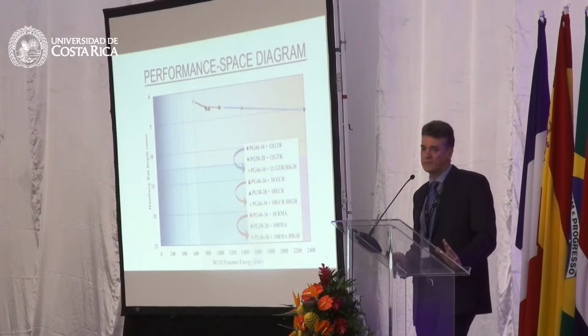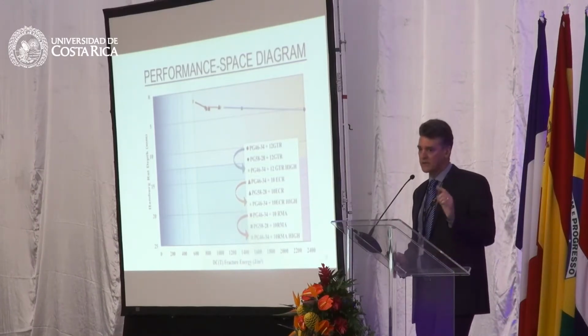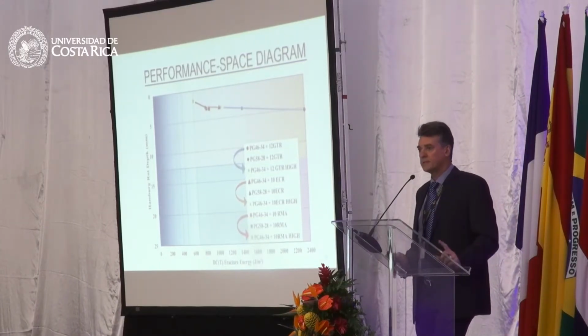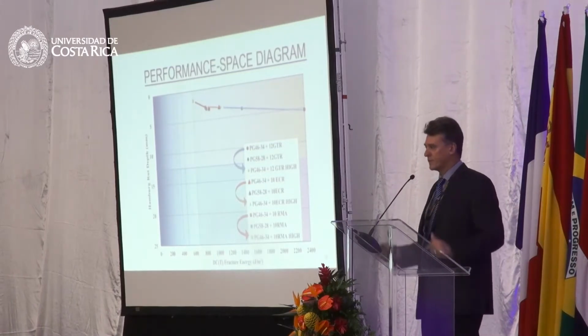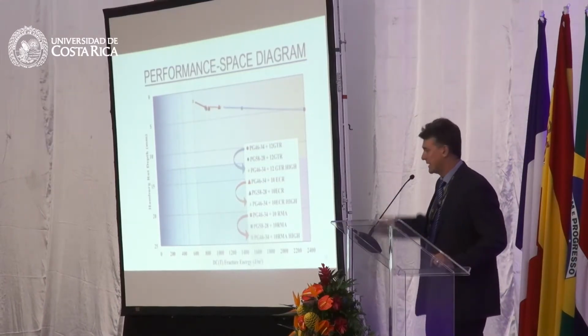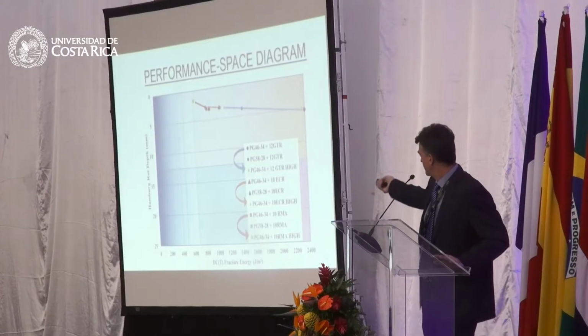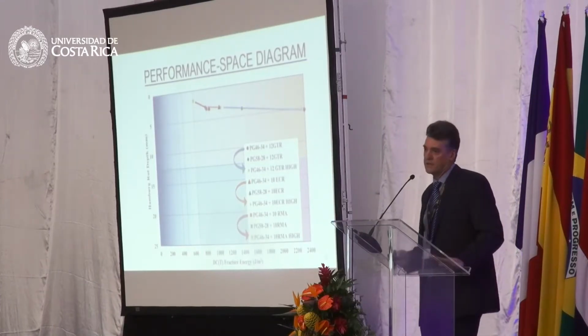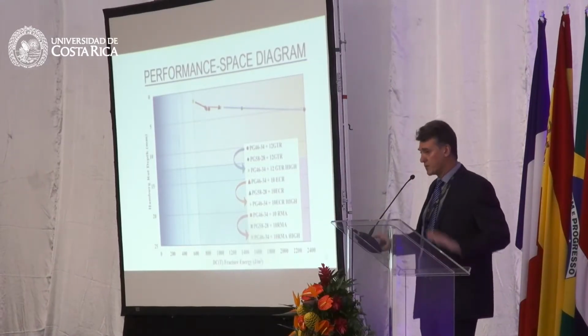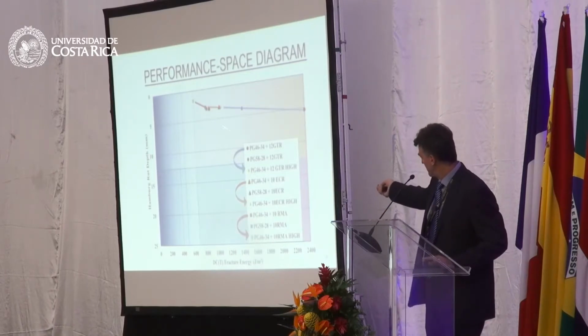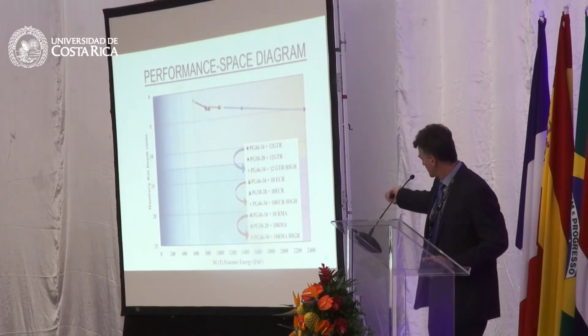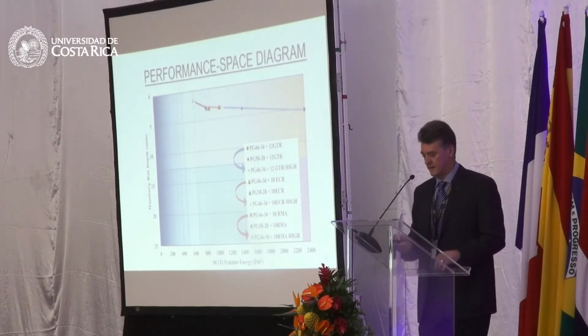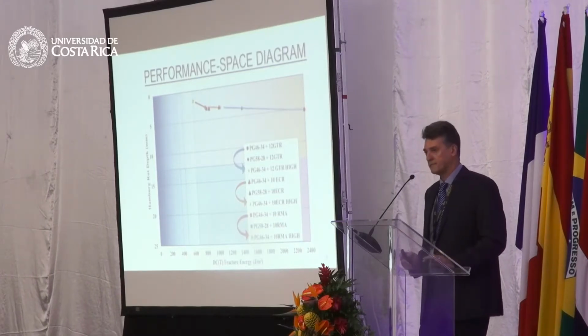It may be that we've been designing these mixtures a little too stiff. They seem to be very tolerant to a soft virgin binder, and that can probably push us pretty far out into the performance space here. Whereas other mixtures, when you use a softer binder, it may push you down more in this direction towards failing the rutting test. So I thought that was pretty interesting.